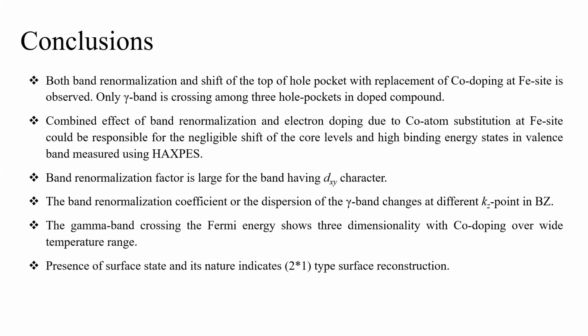This 1-2 compound is stable, but the 1-1 compound is not stable, right? I don't know, but they are stable actually, in the sense that people have looked at them. Another interesting part of these compounds is that both the iron d orbitals and arsenic p orbitals contribute close to the Fermi energy. There is a chance that you will be able to see a band inversion, and because of that, in these compounds people have found all types of topological states, all the topological states that we know till now.